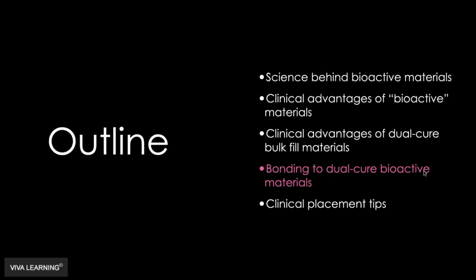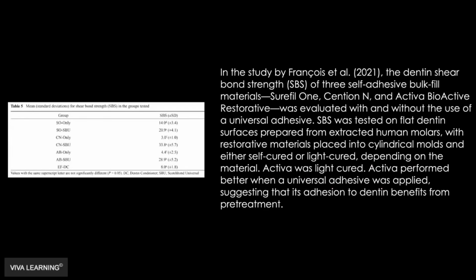All right. The next thing is bonding to dual cure bioactive materials. The first question is, should I use a bonding agent with Activa? And the answer is yes, you should use a bonding agent with Activa. There was a clinical trial, I think, that proved this, but also here's some laboratory bond strength data. AB only and AB SBU. AB only means the bond strength to dentin without using an adhesive with Activa, and you can see the bond strength is 4. AB with Scotchbond Universal shows a bond strength of 29. So you should use a bonding agent when you're using Activa.